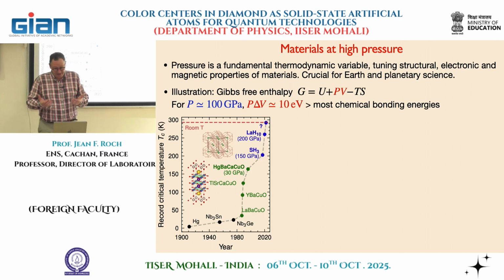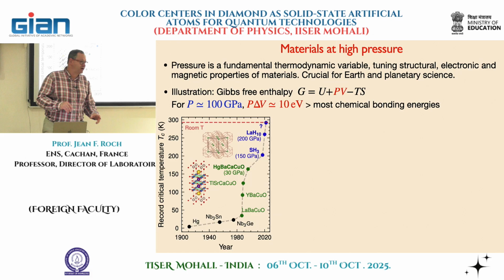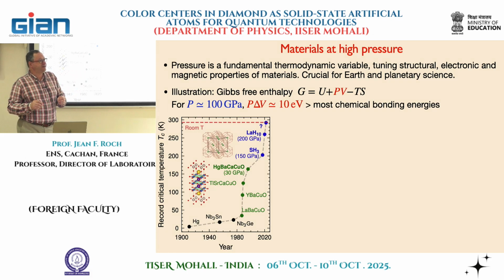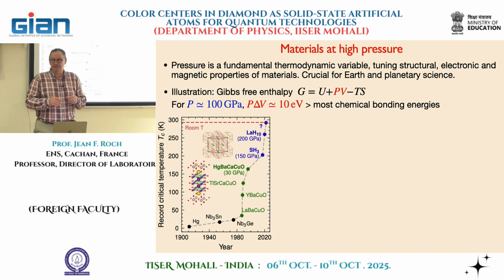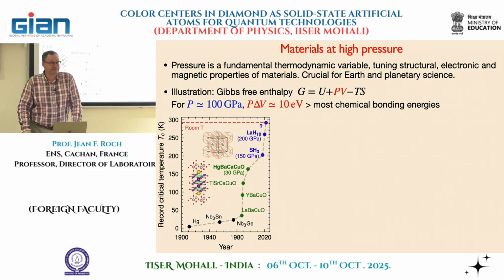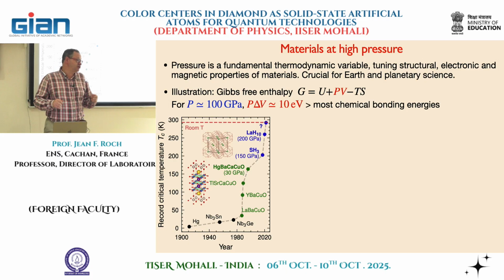But then there was a second step, again a little bit like the idea of chemical pressure, which was to now add another compound with hydrogen, to address other samples, which are called hydrides, in which the structure of the crystal is very close to the one you would have with hydrogen. And those systems were expected to be also superconductors, following the calculation done as a follow-up to the prediction of Neil Ashcroft. And a hydride is the combination of a metal plus hydrogen. But to get that, you need to be at high pressure so that you have samples that have this very specific stoichiometry and structure that is specific to the onset of superconductivity.